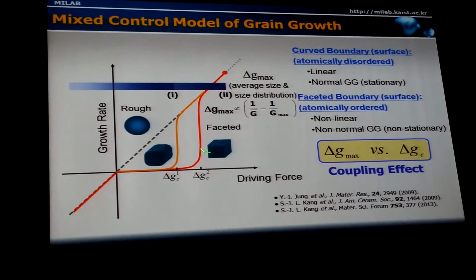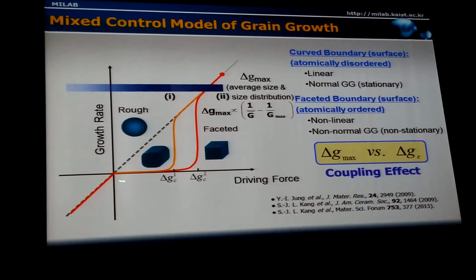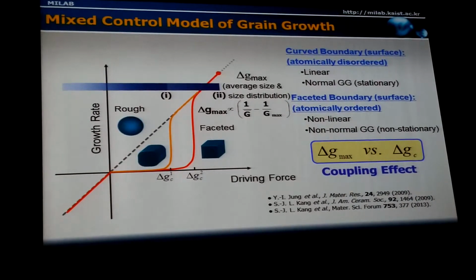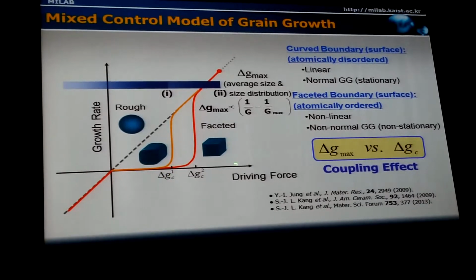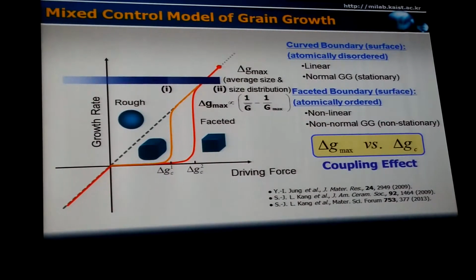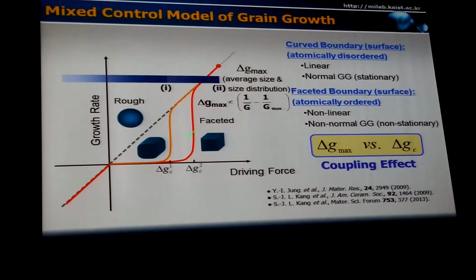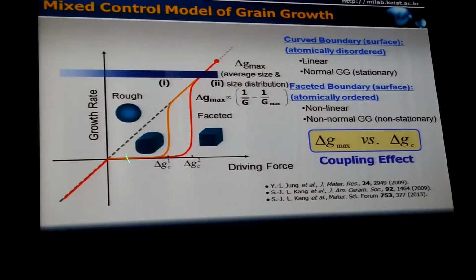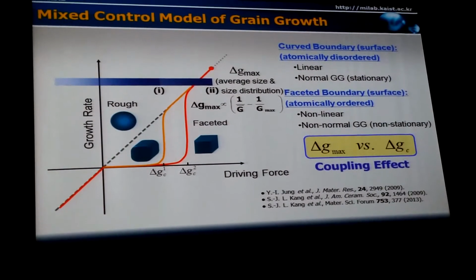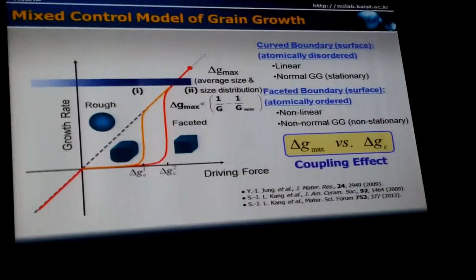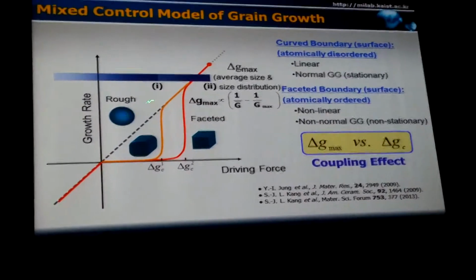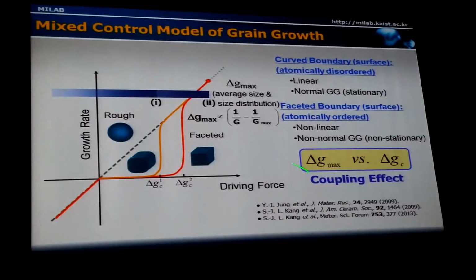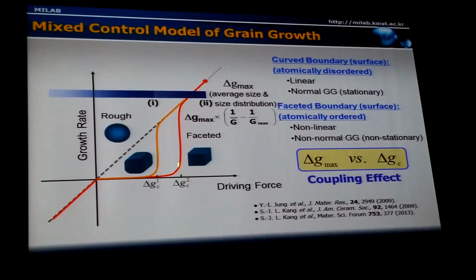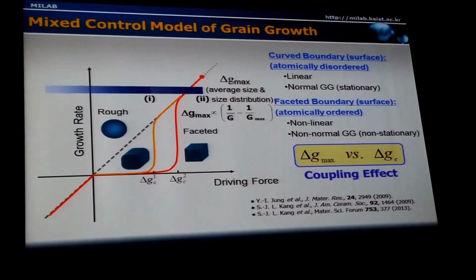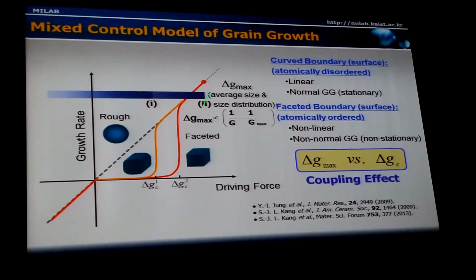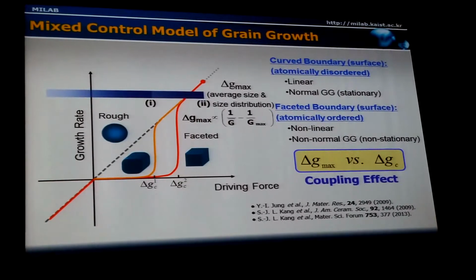But when the boundary is faceted or the grain shape is faceted, then the growth rate is not linearly proportional to the driving force. There is a non-linear region. And so the growth behavior must be non-normal and non-stationary. And the contribution or effect of this nonlinear region to the overall kinetics will govern the grain growth behavior. And quantitatively, we can predict the effect of this nonlinear region by comparing the maximum driving force and the critical driving force. And so there must be a coupling effect between the maximum and the critical driving force in the polycrystal.